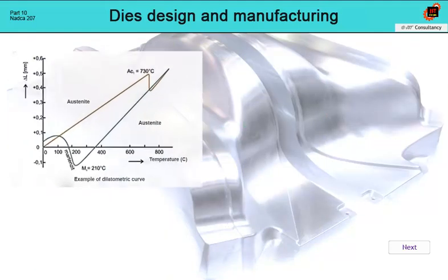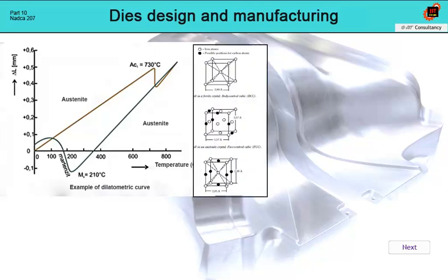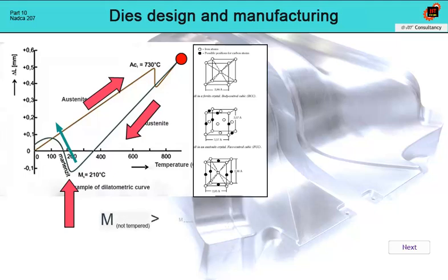This figure shows the dilatometric curve of the change in the size of the crystal lattice during heating and cooling. During heating, due to increasing temperature, the volume of perlite increases up to the point of transformation to austenite. In the next phase, the austenite lattice increases until the austenitic temperature is reached. During quenching, the austenite shrinks as a result of the temperature drop, up to the martensite start point. Here, a critical period occurs when the transformation of austenite into martensite leads to a significant increase in the volume of the structure. For individual structures, untempered martensite is larger than tempered martensite, which is larger than bainite, as well as ferrite. Austenite reaches the smallest volume.